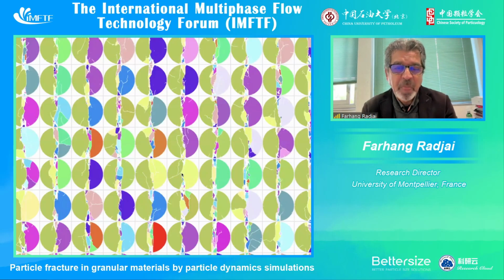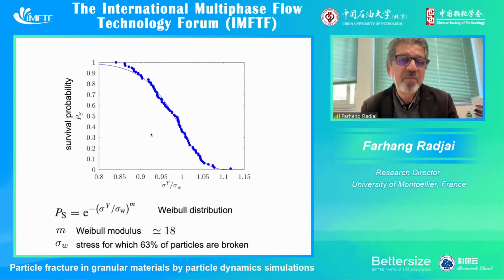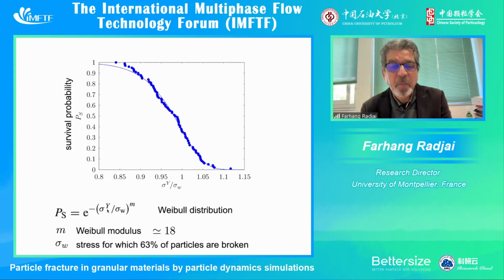Here you see an example of the survival probability of the particles under load. And as you can see, it can be very well fitted by a Weibull distribution, which is shown here. Sigma y is the breaking threshold, sigma w is the characteristic stress, and m is the Weibull modulus. Here it is 18 for the parameters that we used, which is very close to what we have, for example, for ceramics.